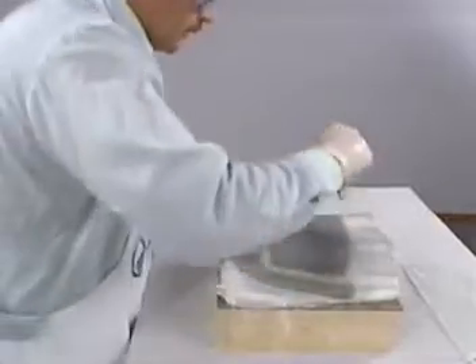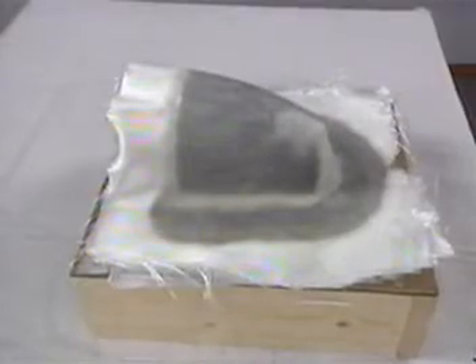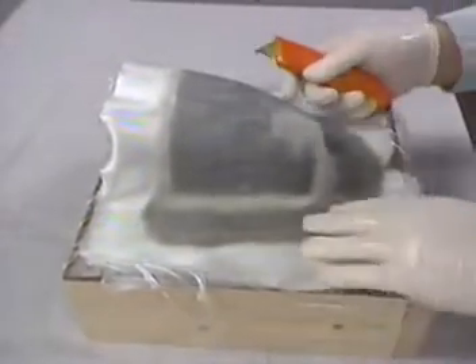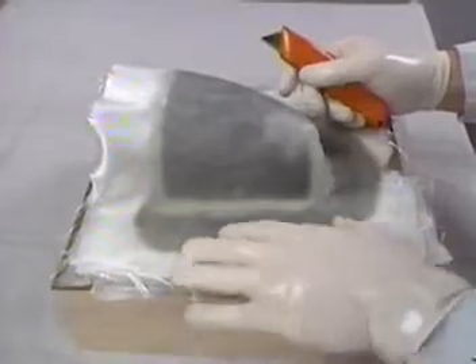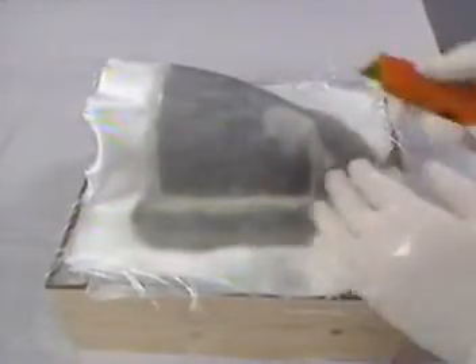There are now a total of 12 layers of fiberglass on the mold. The mold half is now completed and will be left alone for about 30 minutes until it is partially cured, but still soft enough to be trimmed with a knife. Dennis trims the mold, leaving about a 1-inch lip, which will later be used to join the mold halves together.